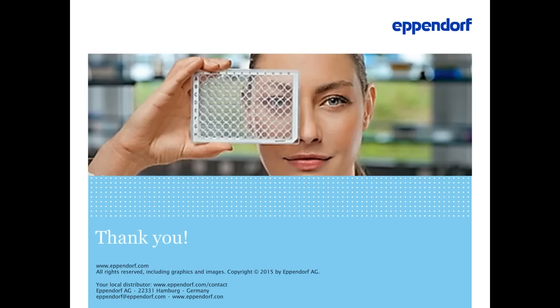Well, I've mentioned there are many classes of different compounds which are UV absorbing and mimic DNA or generally nucleic acids. And it really depends on the consumable. We were doing this internal test. Some of them we provided you here. From my perspective, in many cases, this leaching is very unreliable, so we can have one production batch and different tubes or plates with different leaching levels. So the effect is there, but it's very unstable and unreliable. I would say as a good answer here, or the practical tip is try to avoid tubes which are very clear. Try to avoid suppliers which use the critical additives or avoid confirming the absence, and try to minimize the risk according to these points I've been mentioning in the last section of the seminar.